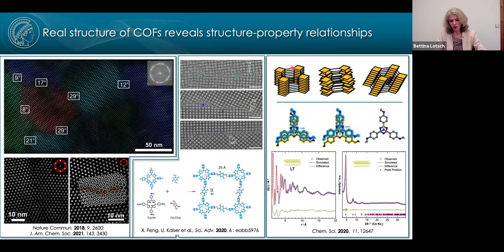And basically 2D COFs are typically depicted simply as being layers that are perfectly eclipsed stacked. So right on top of one layer, right on top of each other. But there's also the sense, and that's very obvious, especially I guess to organic chemists, that if you stack aromatic systems right on top of each other, this is not the thermodynamic minimum configuration. And so what we did quite recently is we used total scattering analysis, pair distribution function analysis, to get an idea of the local structure of covalent organic frameworks.